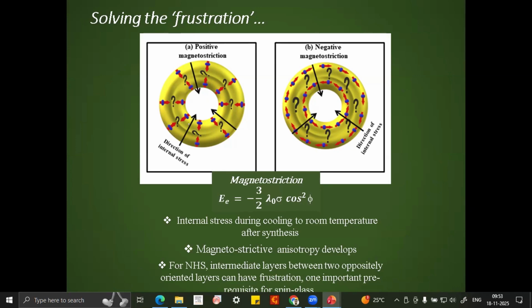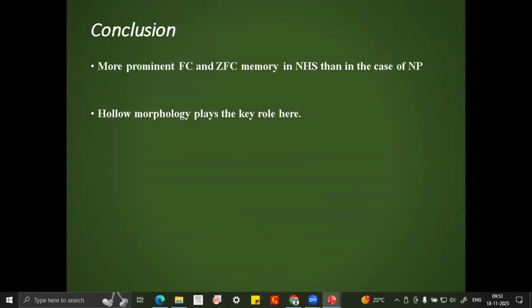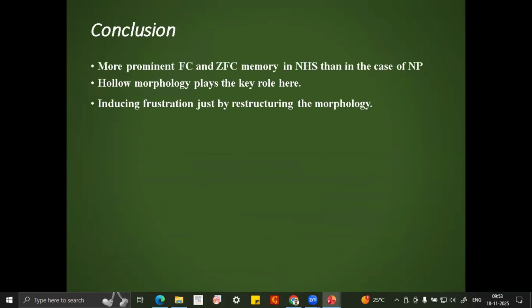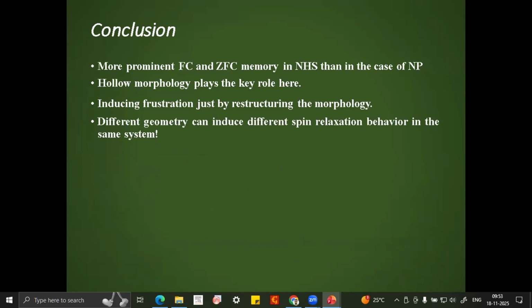So the intermediate layer between two oppositely oriented layers can have frustration. The spins there do not know which way to align. The same thing can happen for a negative magnetostriction sample. Here, phi should be pi by 2, so the moments can orient themselves either clockwise or anti-clockwise. Again, the intermediate layer can have frustration. With this interpretation, I conclude that more prominent FC and ZFC memory is there in the nano hollow sphere than in nanoparticles, we can induce frustration just by restructuring the morphology. And the most important conclusion is that we can have different spin relaxation behavior in the same system just by restructuring the morphology at the nanometer scale.